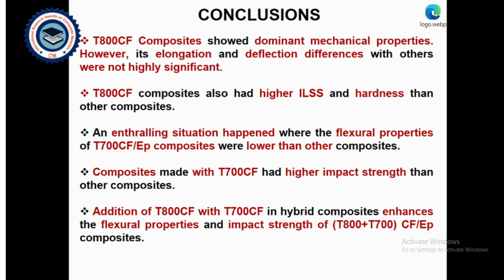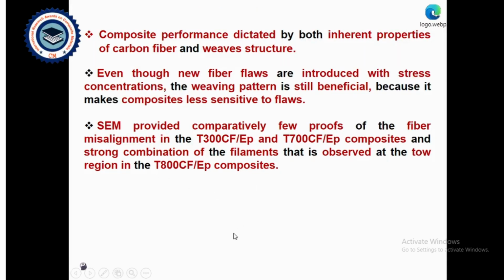Addition of T800 carbon fiber with T700 carbon in hybrid composites enhances flexural properties and impact strength of T800 and T700 carbon fiber composites. Also, composite performance is dictated by both the inherent property of carbon fiber and weave structure. Even though new fiber flaws are introduced with stress concentrations, the weave pattern is still beneficial because it makes composites less sensitive to flaws. Finally, the SEM provided comparatively few proofs of fiber misalignment in the T300 and T700 carbon fiber composites, and a strong combination of filaments was observed in the T800 carbon fiber composites, and hence T800 showed better properties in most of the properties.